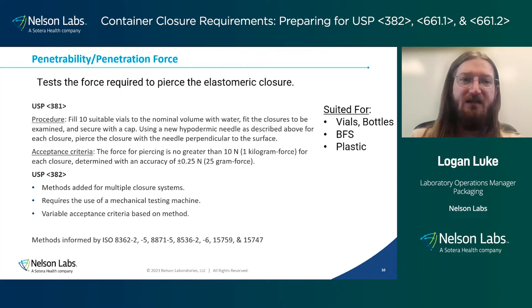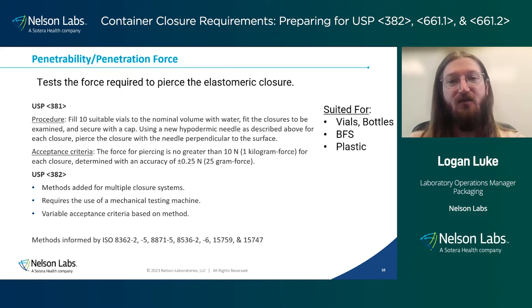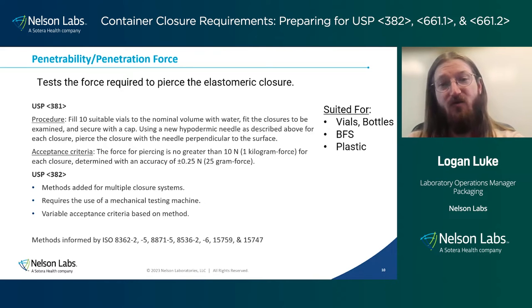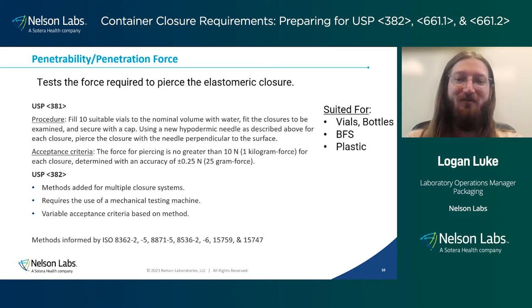On these first slides, I've included the entire procedure of these tests as they were contained in 381. And I did this to highlight the fact that these were very simple tests in USP 381, and in USP 382, they have been built out considerably. The test itself, though, is measuring the force required to pierce the elastomeric closure. And this confirms the ability for the closure to actually remain in place also while you're piercing that elastomeric closure.